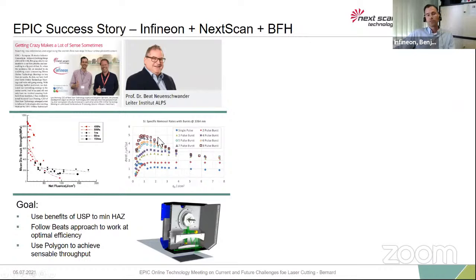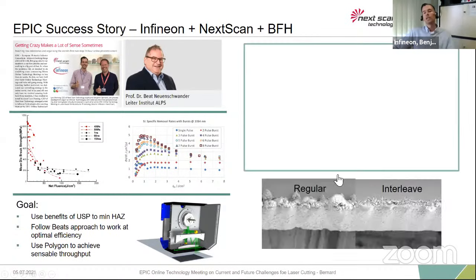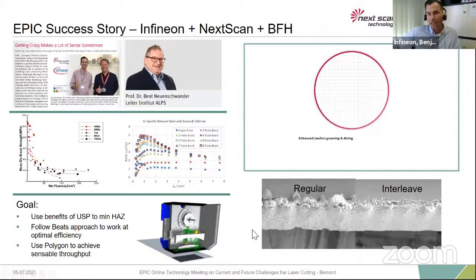And therefore we tried to follow Beat's approach. That means we were sitting at the highest efficiency, but as you can directly see, you're then working with low fluences. And therefore you need to be fast. You need to do many overscans. And here Lars comes into the game, who's delivering the right equipment, the polygon scanner with a 300 millimeter scan field.